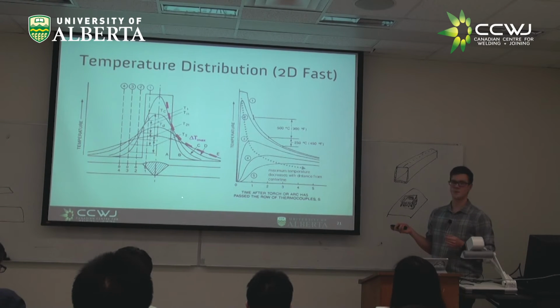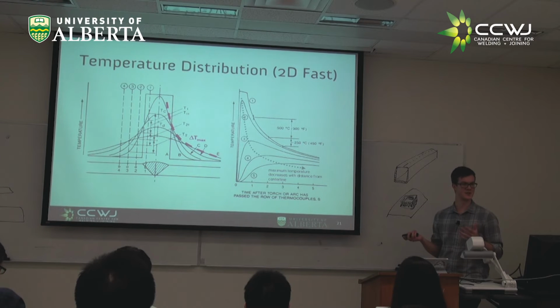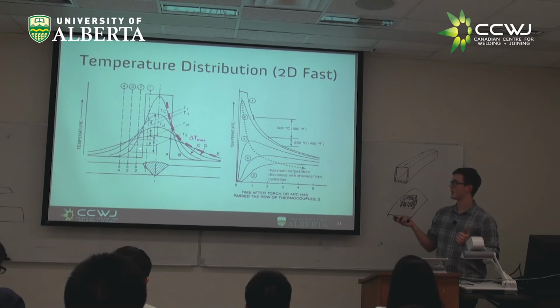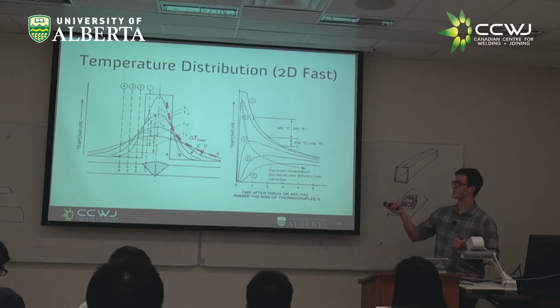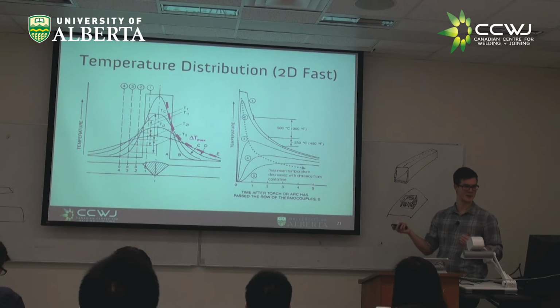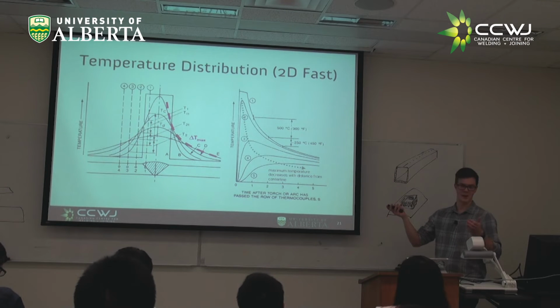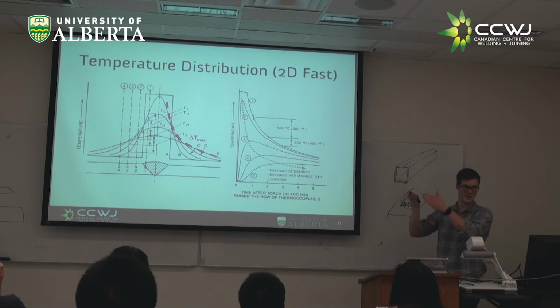So I think this would have been probably a couple weeks back, but we talked about what that peak temperature distribution looks like in welding. If you imagine you have a weld and you initially apply some heat, you start at this point here. Most of your heat is very close to the weld, right? And as you cool, you end up with what looks very much like a Gaussian distribution that just gets flatter and flatter. So this would be if you're looking down the weld seam, right? You have some time 0 where most of your heat is near the weld, then some time a little bit later where some of the heat that was here is now spread wider, a little bit later some of the heat in the middle spread wider again, and it gets wider and wider.